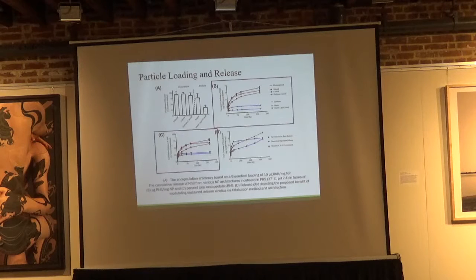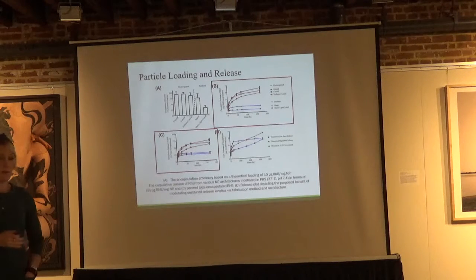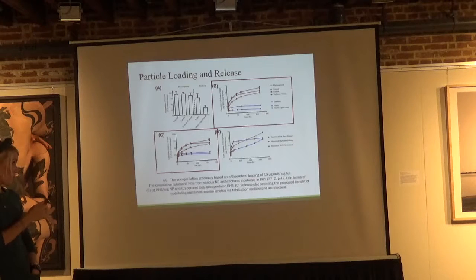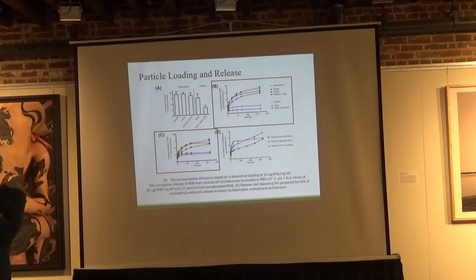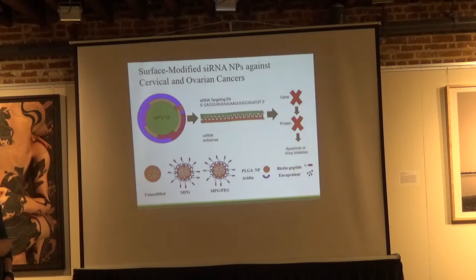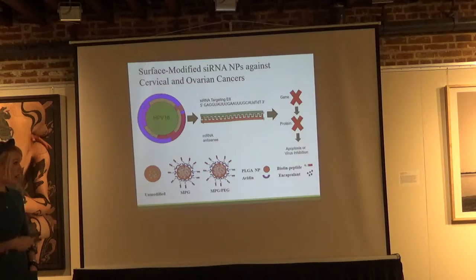Here in panels B and C, I just want to show, as a function either of the amount of a small hydrophilic agent, rhodamine, mass per mass, or as a percent total loading, how we get much more favorable release characteristics here just over a period of 1 week for either our uniaxial or the two variations of coaxial. And we're looking at moving this forward. Currently we're trying different polymers, polymer blends, and solvents to actually get our sizes down to make them similarly sized to our emulsion-based fabrications. And we're hoping to continue our work to go back and apply this